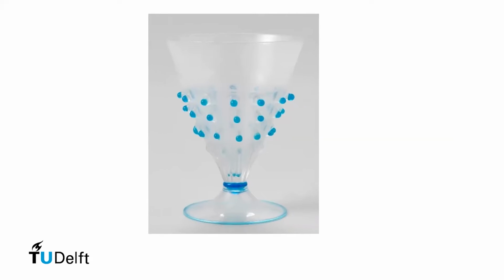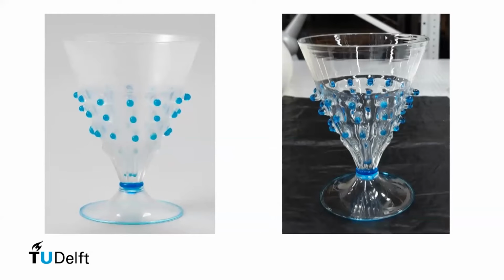So if you go to the next slide now, we can see the difference here, where ion chromatography analysis showed that this matte appearance was actually the result of moisture accumulation again. In this case, specifically as a result of sodium formate salt, which is quite hygroscopic, so it attracts water quickly, and it dissolves in water. So the cleaning procedure was fairly easy: remove all the salts, remove the water that might damage the glass even further. And now it looks like this again. Next slide, please.